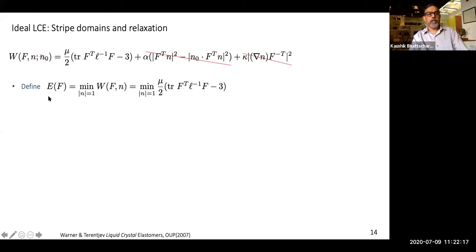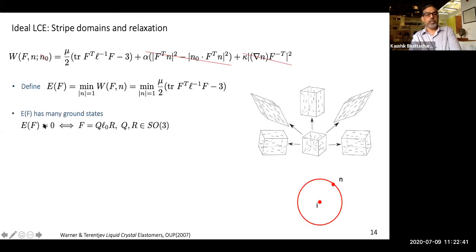So what I'm going to do is to define an elastic energy, which depends only on the deformation gradient, by minimizing this director out. So that's a minimization that you can actually carry out by hand. And what you find is that the ground state of this is a set of states where this F transpose L inverse F is actually equal to identity. So it turns out that it has a lot of ground states. And if I were to think about it physically, it means at high temperature, if I took a cube, when I cooled it down, it would become a rectangular cuboid. But it can elongate not only in one direction, but in multiple directions. And these are all possible ground states. So the energy somehow looks like this. It is zero on this entire manifold of shapes, and it grows away from it.